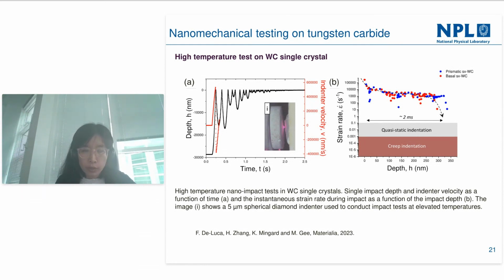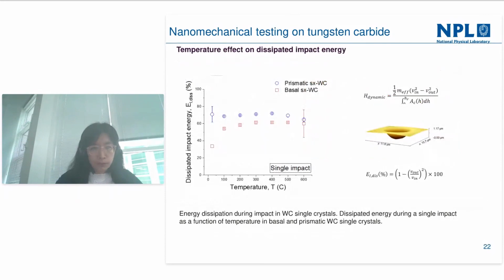So we can achieve a large range of strain rate from 10⁻³ up to 10³ or even higher. The impact test is carried out at up to 600 degrees C here, and we will compare the results with quasi-static at a similar temperature for both grains. Here to mention, for the nano impact test, we used a spherical indenter with a radius of 5 micron, a pendulum acceleration distance of 25 micron and an acceleration force of 5 millinewton.